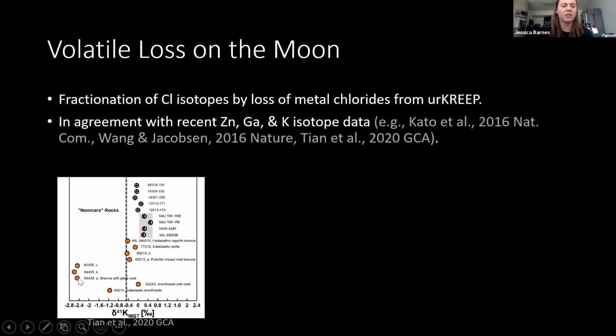So some of the breccias are showing very light potassium isotopic compositions, which actually agrees with some of the chlorine isotope work, which shows that some of the really brecciated regolith samples from the surface of the Moon likely have deposited light chlorine within those breccias. And so maybe these light values in the very heavily processed impact samples are recording a light chlorine vapor deposit.